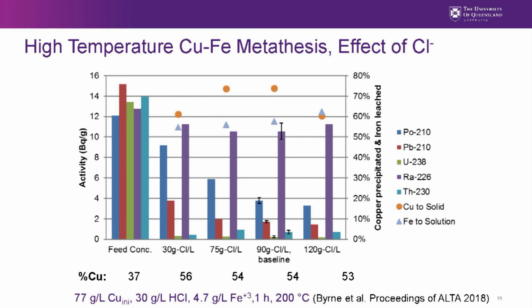Also on this graph, we have these orange circles and blue triangles. The orange circle represents the copper precipitated, and the blue triangle represents the iron dissolved. So high numbers for both imply a high extent of reaction for the metathesis reaction itself. In this case, separating radionuclides is one factor, but upgrading the concentrate is another factor. So you can see that for copper, there seemed to be an optimal chloride concentration where copper was precipitated from solution, and that's the objective here. And then iron seemed to be slightly more dissolved as a function of chlorides. And down below, we just have a summary of the grade of copper. It started off at 37% copper, which is already probably pretty high. And then we upgraded it to between 53 and 56% copper using this metathesis step.